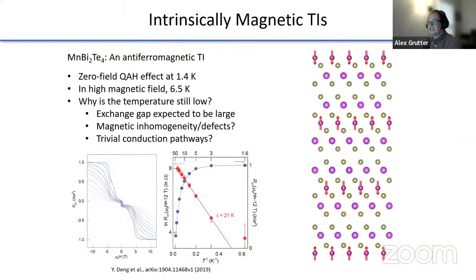And one of the directions people have gone in order to address this is to look at manganese bismuth telluride or other intrinsically magnetic topological insulators. So instead of doping now, we're looking for a material that has an intrinsic long-range magnetic order. And in this case, basically you have a structure that looks something like this. You have manganese monolayers separated by a bunch of bismuth and tellurium, and these are antiferromagnetically ordered. But you can break the symmetry with a large magnetic field and get all of these magnetic moments to point in the same direction.